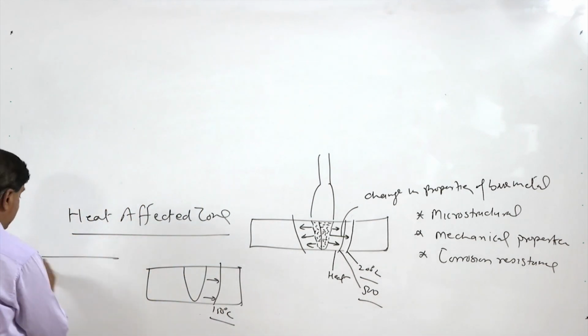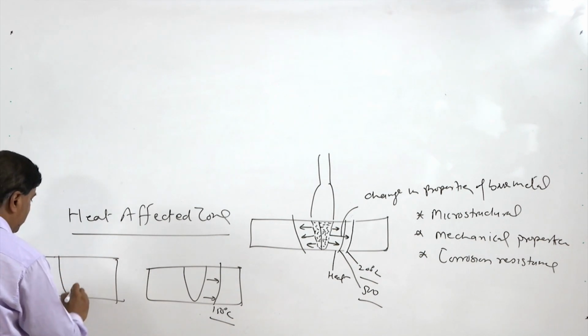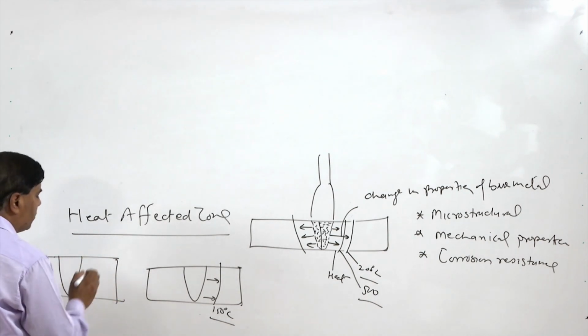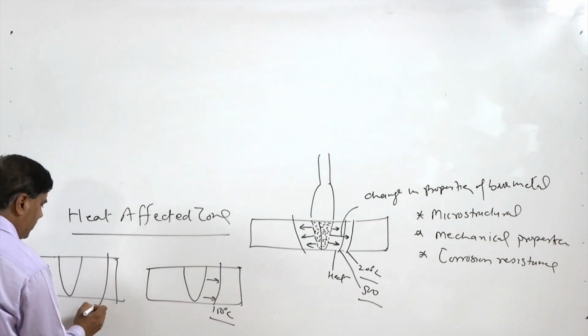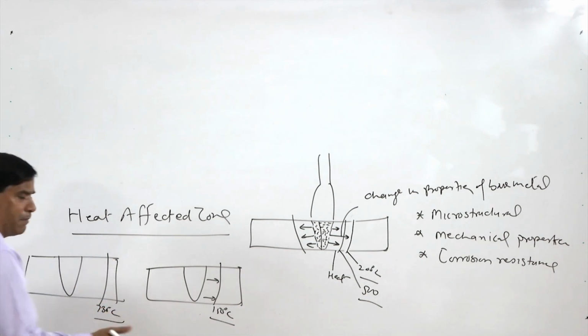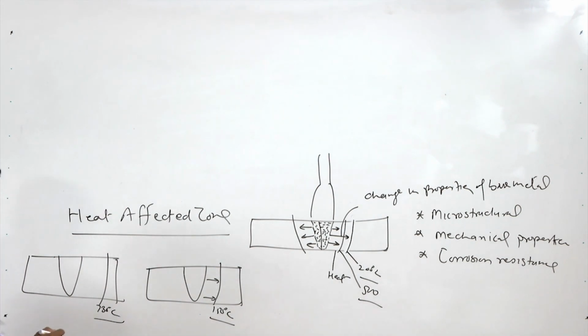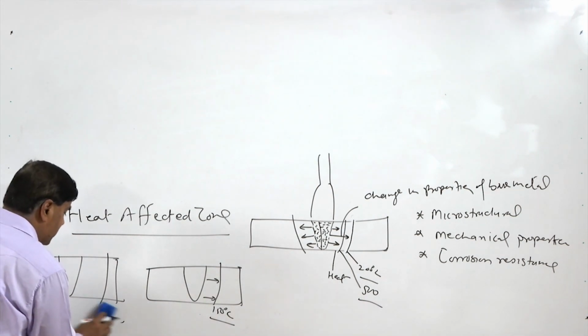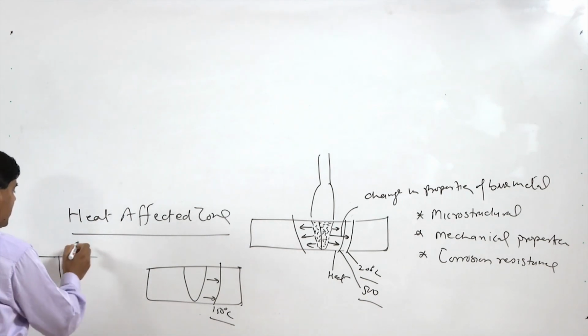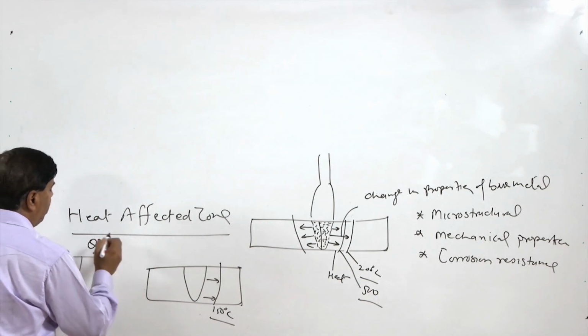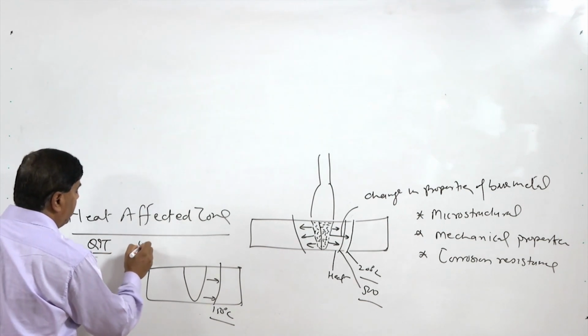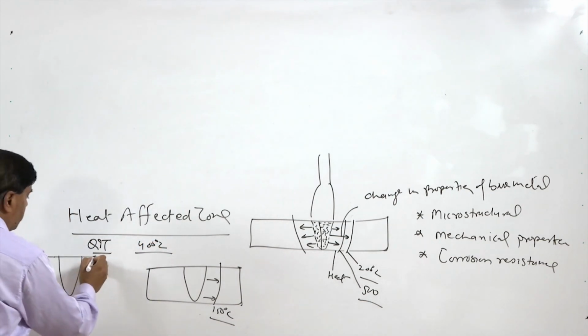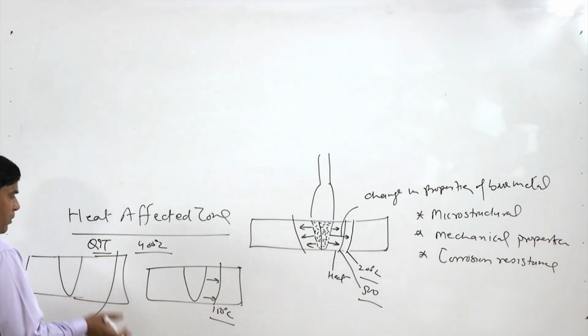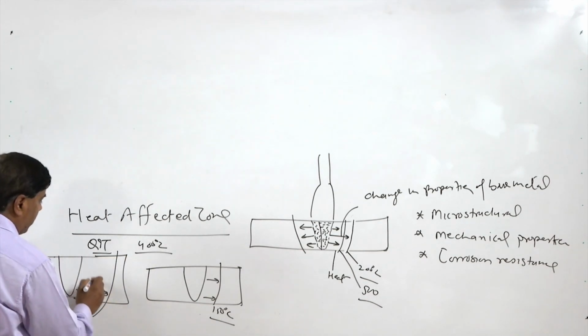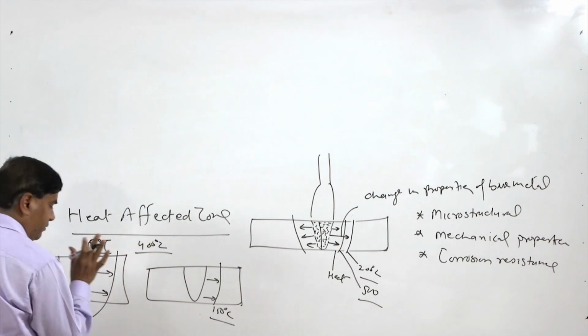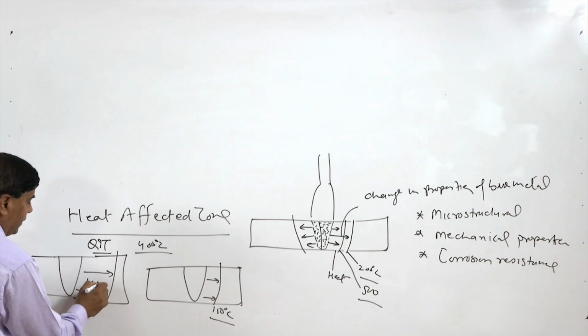In the case of steel, say carbon steels, in normal conditions the regions heated above 730 degrees centigrade, like carbon steel in an annealed condition, fall in the heat affected zone. If it is in the quenched and tempered condition, say Q&T steel tempered at 400 degrees centigrade, all the regions heated above 400 degrees centigrade will be over-tempered. So, all the regions away from the fusion boundary heated above 400 degrees centigrade will fall under the heat affected zone.